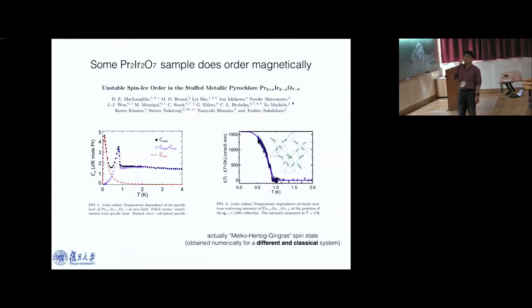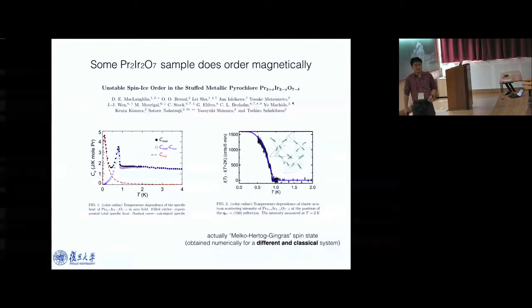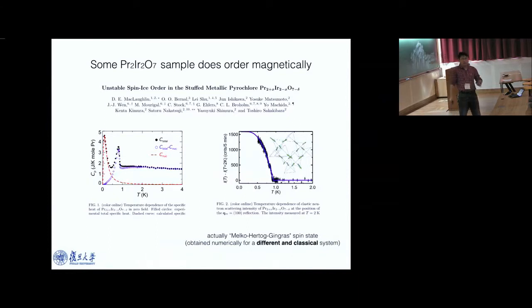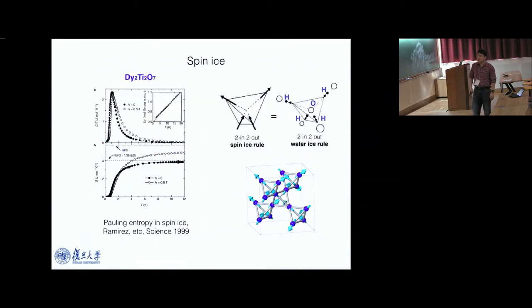The reason why the system develops magnetic order is that after you change the stoichiometry, the Fermi level is shifted up and down. So the induced RKKY interaction is different for different samples, and that's why some samples tend to develop magnetic order. So that's the neutron diffraction measurement. The material is rather complex. The conduction electron is doing something very interesting, and the local moment is also doing something very interesting. Right? A lot of interesting physics is going on in this material.